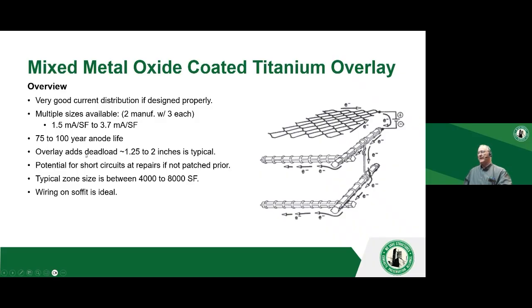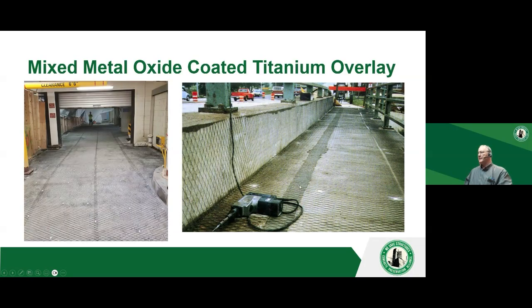And the big issue with the overlays is you're going to lose a little bit of headroom, a couple inches. An inch and a half to 2 inches is pretty typical, and you have some additional dead load. So you've got to make sure your structure is solid enough before you do this. And a typical zone is between 4,000 to 8,000 square feet, and you wire this thing together on the bottom of the slab. Here's a couple pictures of an installation.